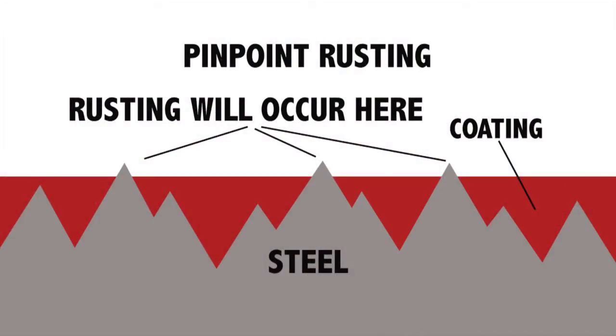While an inadequate surface profile depth may not properly anchor the coating system and debonding may occur, an excessive surface profile may cause rogue or unusual peaks to protrude above the coating film, causing pinpoint rusting and accelerated corrosion. Therefore, accurately assessing the surface profile depth for compliance with the project specification is paramount to a successful coating project.